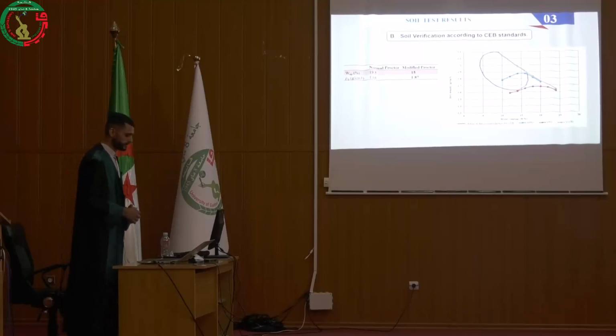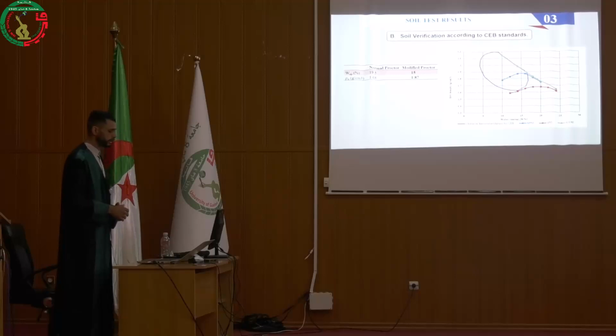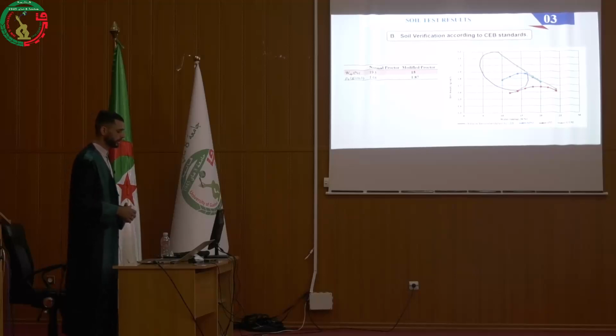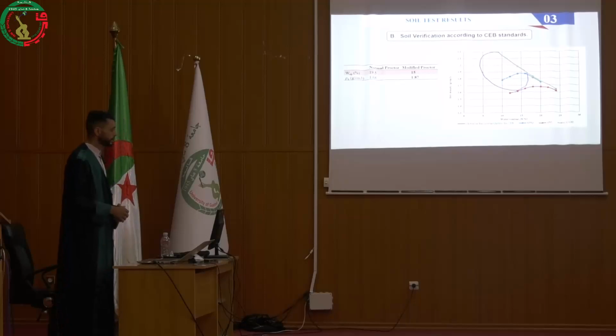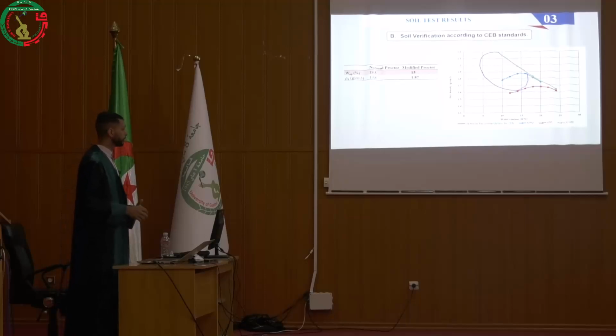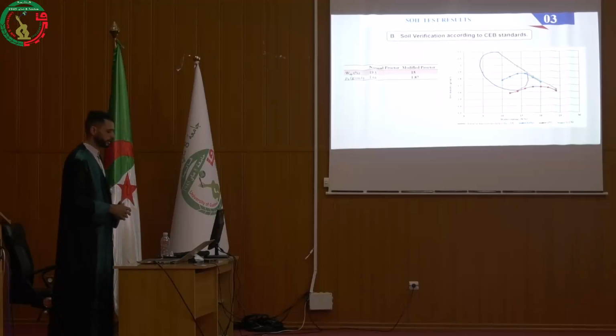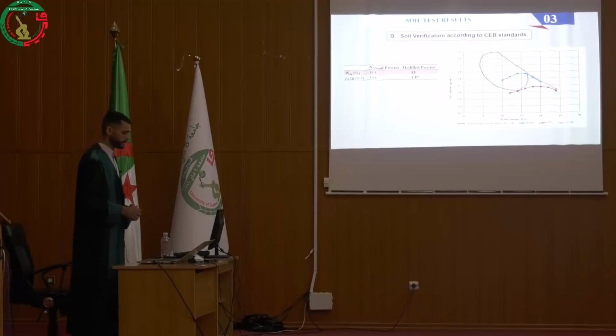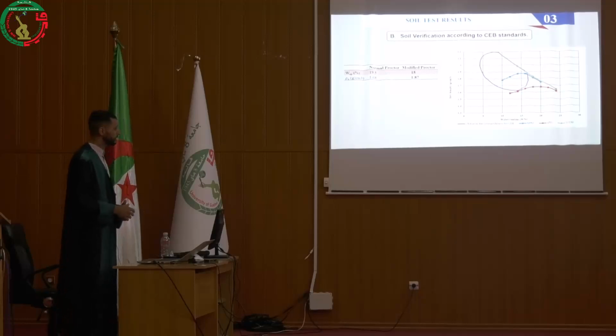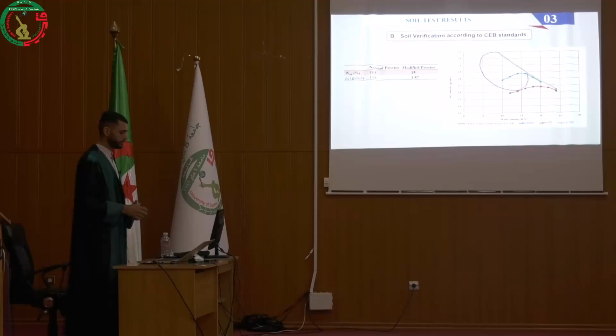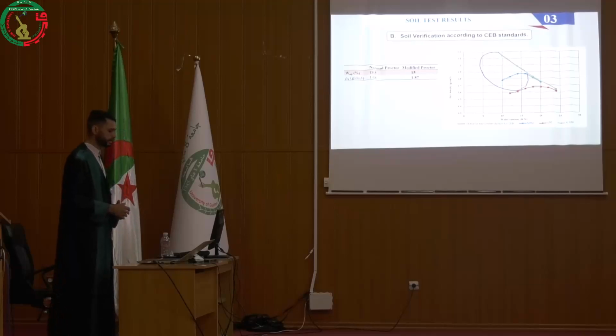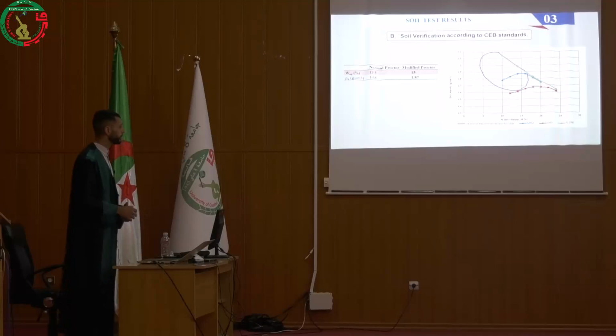Compaction characteristics reveal the soil optimum moisture content and maximum dry density, which are essential for achieving the desired strength and stability in constructed walls. As we can see, the combination of normal Proctor optimum moisture content and maximum dry density falls outside the recommendation range, indicating that this combination is not suitable for the production of the CEB. However, the combination of modified Proctor moisture content and maximum dry density falls within the recommendation range.